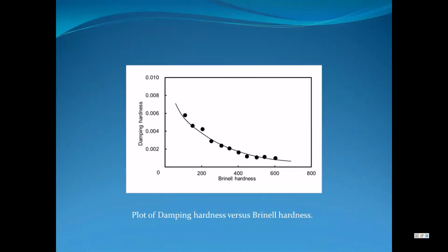One of the authors defined the damping factor as the damping hardness, because the damping factor is considered a physical quantity related to hardness. The damping hardness correlates with Brinell hardness number, as is evident from this figure, and is considered to mean resistance to work hardening. The relationship is a negative correlation, which means the harder the material, the smaller the value of the damping hardness. A harder material would result in poorer accuracy for the damping hardness as suggested in this figure.